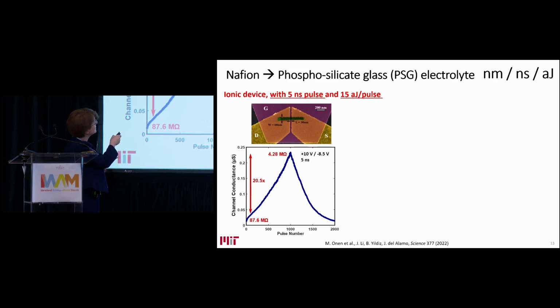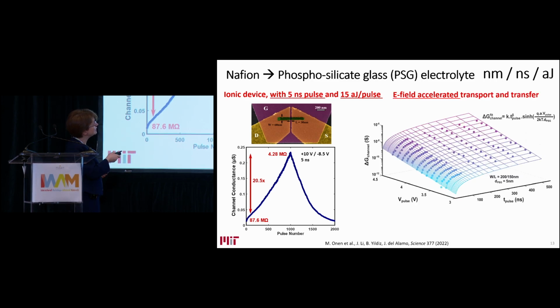And in this miniaturized device with so short pulses, we could also obtain our projected extremely small energy consumption of about 15 attojoule per programmed state. So that's very exciting, but it's not the end of the story or the challenge, as I will highlight in a few minutes. And interesting to note, which I will also come back to later to leverage, is the behavior of these devices where we are electrochemically trying to push ions or protons through is strongly nonlinear with applied voltage.